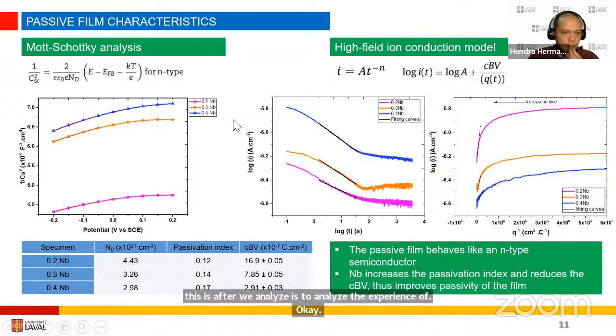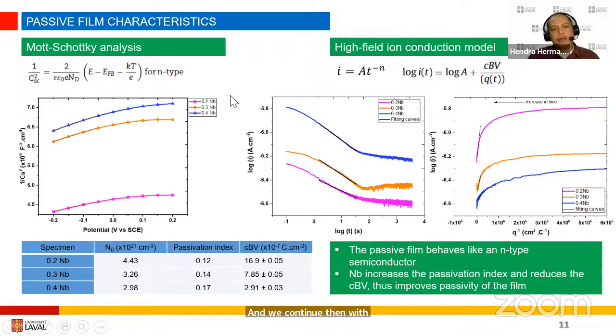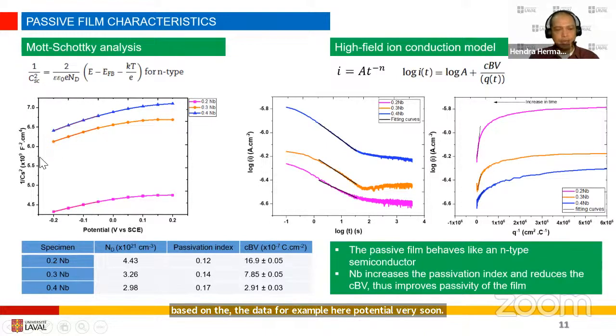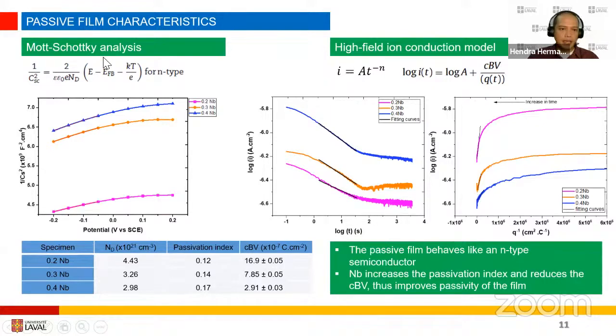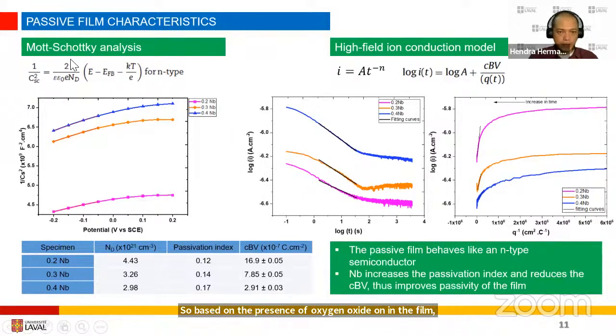and we continue then with some mathematical modeling. So based on the data, for example, here potential versus charge, during the potentiostatic test, we use the Mott-Schottky analysis using this mathematical equation. So based on the presence of oxide in the film, we conclude that the passive film is an N-type semiconductor. So we use this equation. And from that, we can identify the number, the donor number.